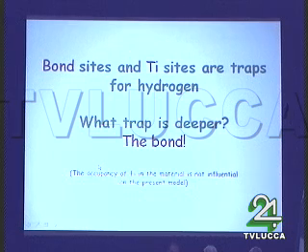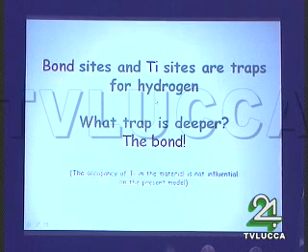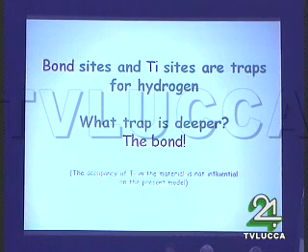After re-equilibration, the deeper sites are occupied. And what are those deeper sites? Bond sites and titanium sites are both traps for hydrogen. But the deeper sites are the bonds, because the experiment shows that the peak decreases.